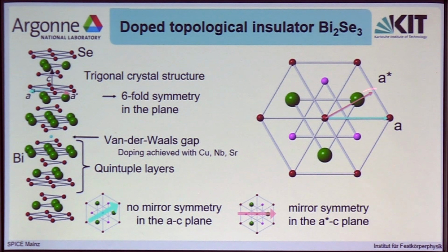Now, for the in-plane symmetry, there are two very important axes in the system. There's the a-axis and the a-star axis in this trigonal crystal structure. And I already want to point out there's a clear difference between those two, namely that the a-axis itself is not a mirror axis in the system, whereas the a-star axis actually, as you can see here, is a mirror axis. We will need this later on.